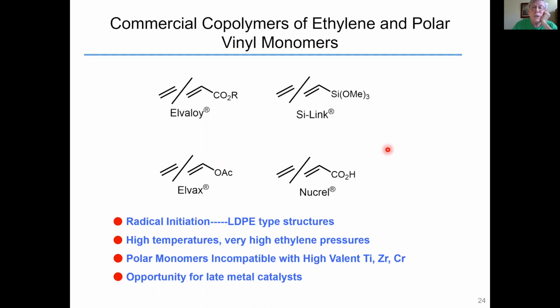The advantage here is that, for example, in this case, and I'll say something about that later, you can cross-link this material and generate very, very tough cross-linked polyethylene. In this case, you can generate the salt here and cross-link these through a divalent cation. For example, the covers of golf balls involve these cross-linked materials via this carboxylic acid group.